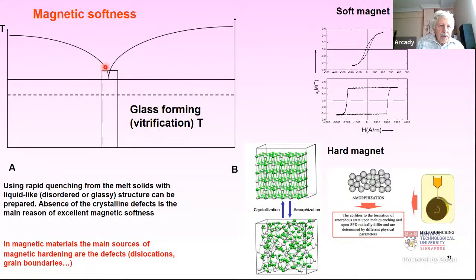When you have deep eutectic, and then you can quench very fast from liquid state to solid state and fix a classic glassy state at room temperature. And this amorphous material does not have defects typical for crystalline materials like grain boundaries, dislocations, etc. So it's one of the main origins of magnetic softness of that kind of materials.